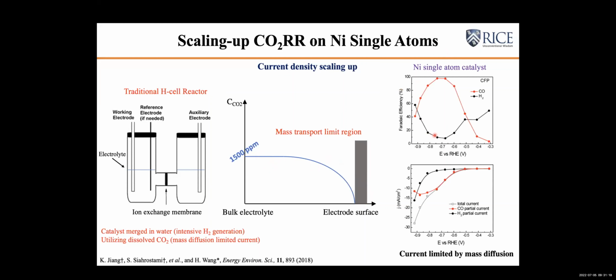So in H cell reactors, we always see the CO selectivity ramp up to 90 or even 95% to a maximum. And then if you want to apply more and more negative potential to ramp up the current density further, right? You won't see the CO current density further ramped up. Actually, as a result, you will see the selectivity of CO start to drop. As a result, your hydrogen starts to pick up because you run out of surface CO2. And there are a lot of water molecules. They can also pick up the electrons to generate hydrogen. So this will always limit your current density to about 10 to tens of milliamps per centimeter squared.